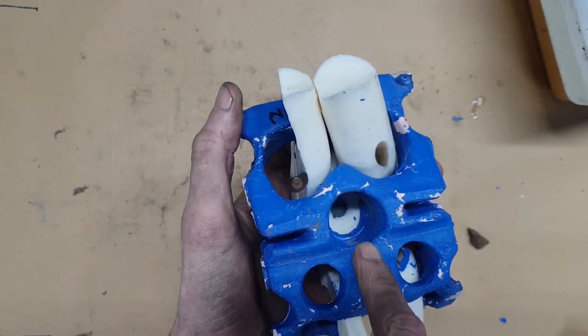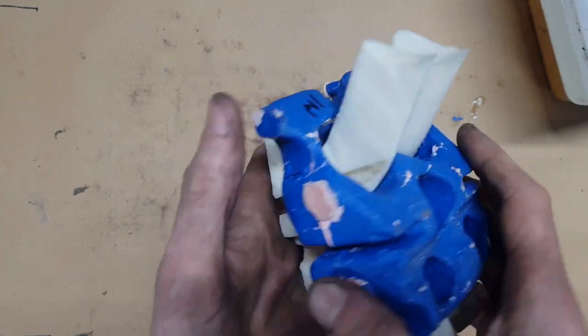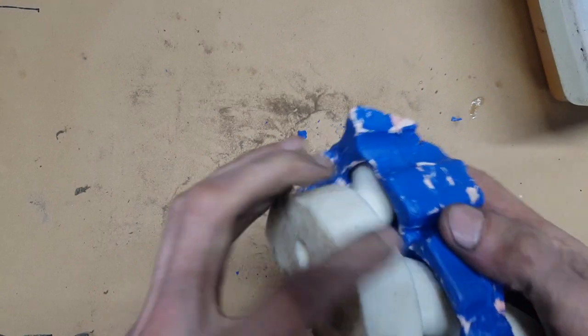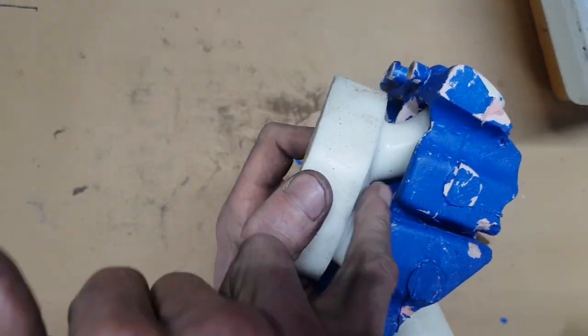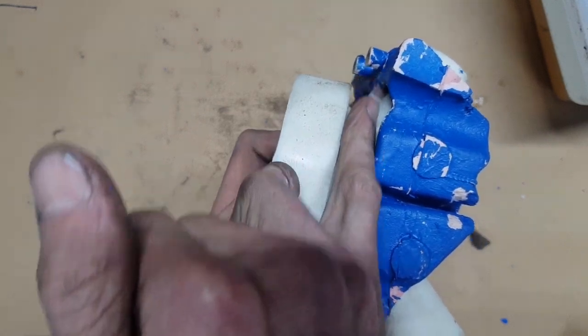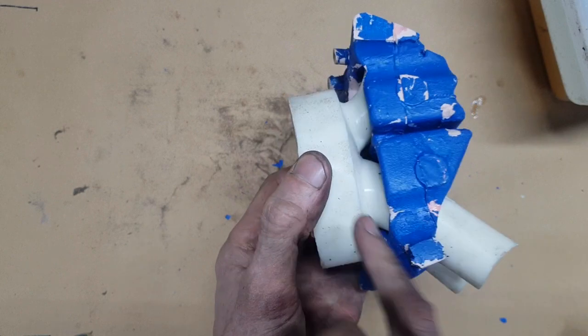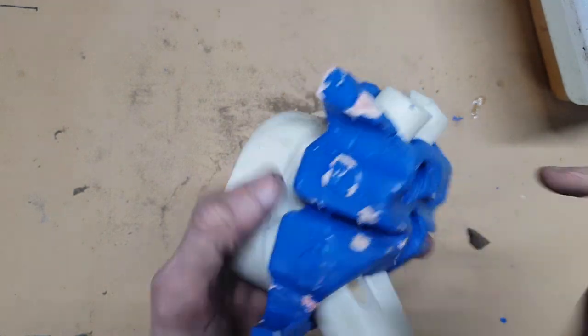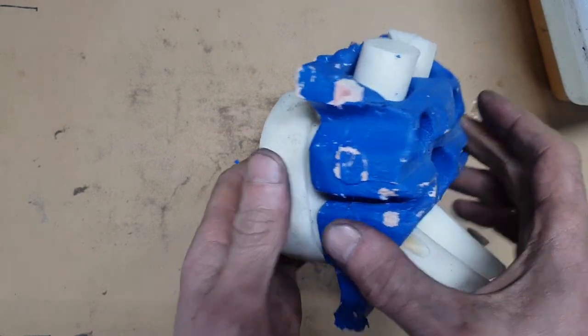Yet you'd have a huge mass of aluminium here that they needed for the spark plug boss. And again, if I just remove it off a small bit, just to exaggerate it, you'd have a huge amount of aluminium here and all the way around here on the deck face, which would also solidify last and be sucking aluminium from this solidified zone, which will cause cracking.